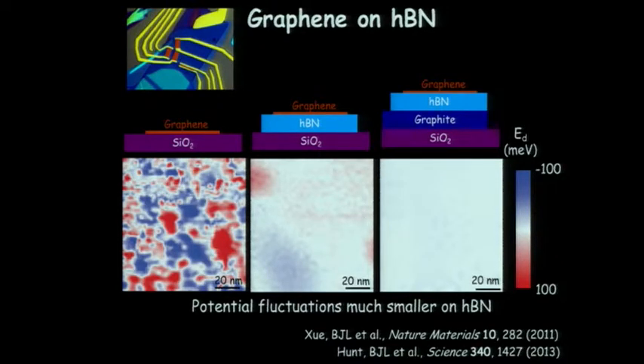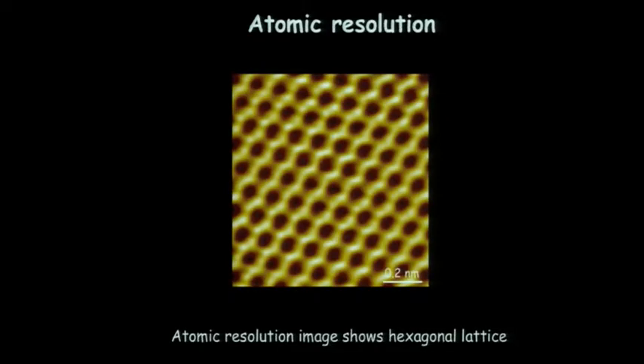All right. So this is basically showing that using the HBN did exactly what we wanted. We got much better, cleaner graphene devices without having any modifications to the graphene's properties. And if you go and look now at the atomic scale images here, you can get very nice atomic resolution images of the graphene lattice because it's now sitting on a very flat substrate. Before it was on this very bumpy oxide, it was hard to see the lattice. But here we get nice atomic resolution.